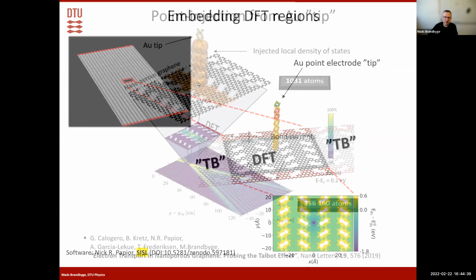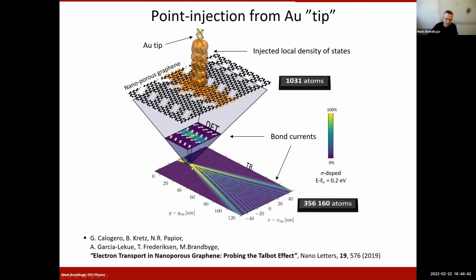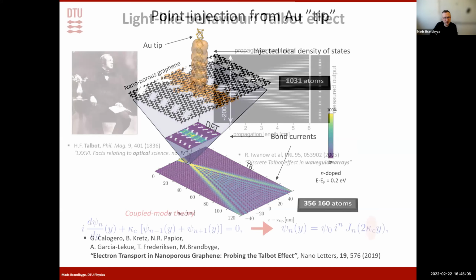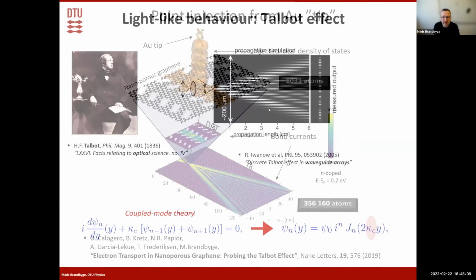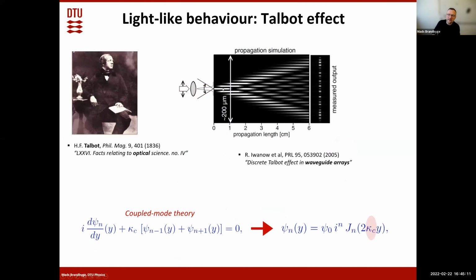And somewhat to our surprise, when we did this, we saw that it's making this kind of interference pattern, the current. So we inject current here from the tip, and then it's spreading out, making this interference pattern. And the interesting thing about it, among others, is that this interference pattern is something which is well known from optics way back. It's called the Talbot effect. And this is something you see when you have optical waveguides which are coupled relatively weakly. Then you get this kind of Talbot interference pattern.